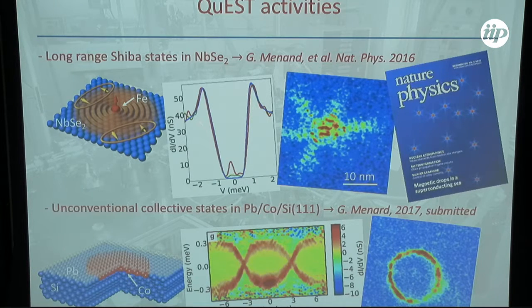the quasiparticle excitation spectrum. Now, if you go from the center of this island and go away, you see that these two peaks shrink and merge to one peak at the Fermi level, then split again and merge again as you go away. This state at zero energy has characteristics of Majorana statistics, and if you look at how it looks in space, you get just a very nice ring. This is a recently submitted paper.